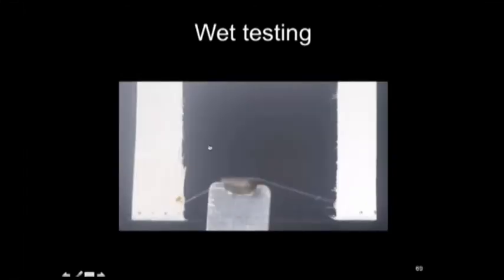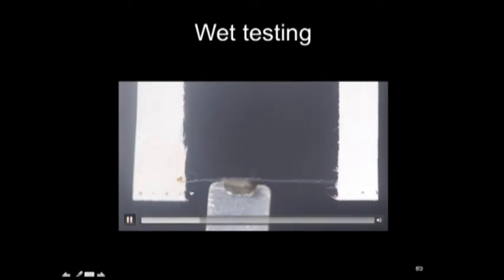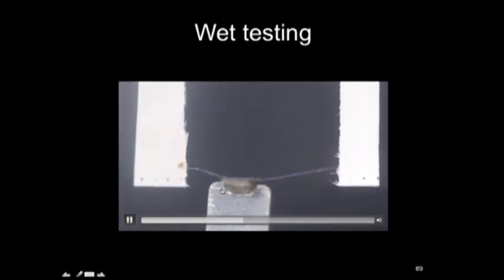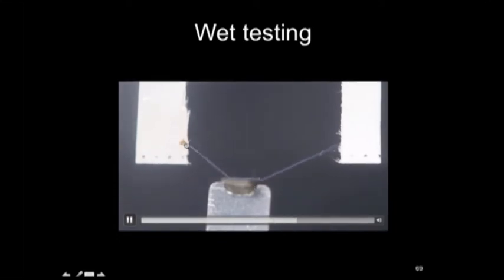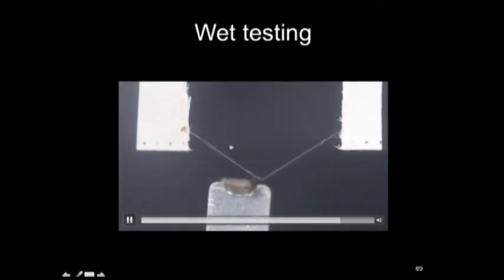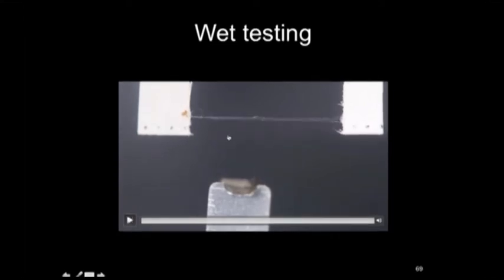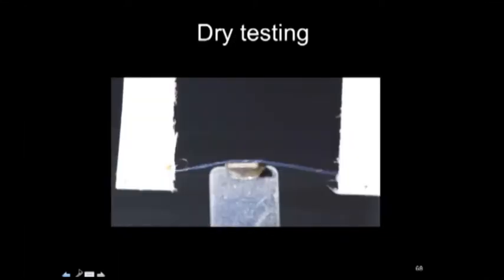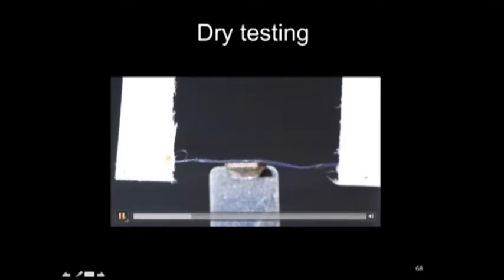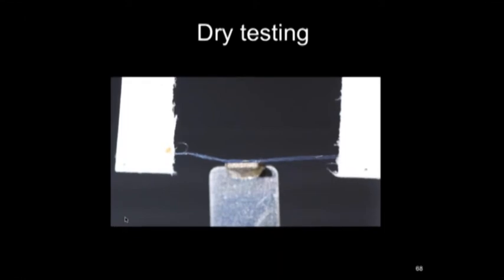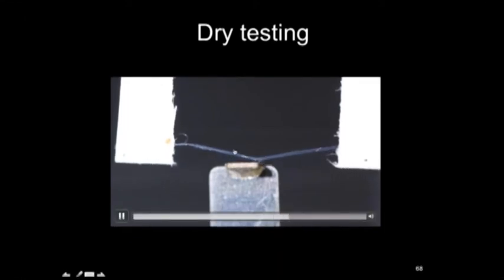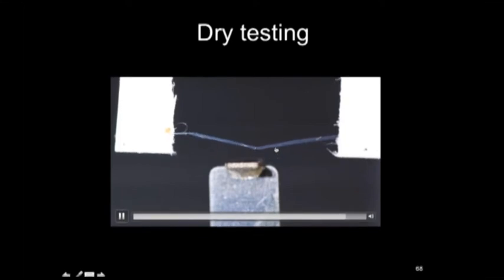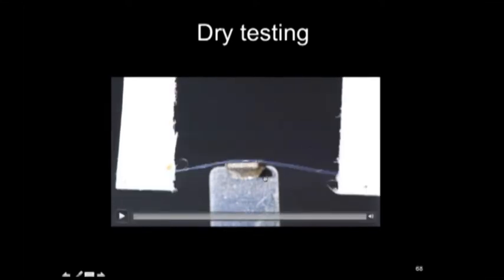I'll go back, just in case you missed it, to have another look at the difference between these pull-off behaviors. You can see again that these axial fibers underneath don't seem to deform very much, and really they only bend slightly, and it seems to be those cribellate fibrils, those blue-hued fibrils, that do most of the deformation. Whereas here, I'll play the video once more, we can see that the underlying fibers and fibrils deform much more and actually do stretch while attached. And we can see it's much more dramatic.